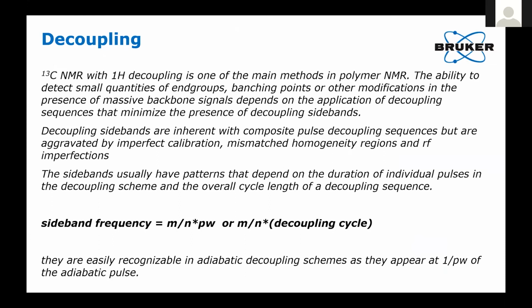One of the major issues in carbon-13 NMR of polymers is proton decoupling. Because what happens is that most of the composite pulse decoupling schemes will give you a certain amount of sidebands. And these decoupler sidebands appear at positions which are related to the pulse width of the decoupling frequency and also the decoupling cycle.